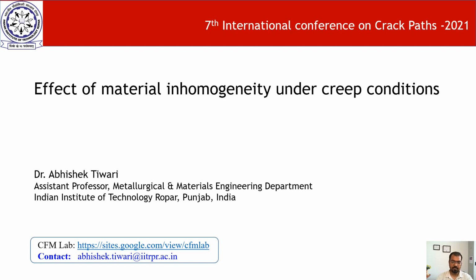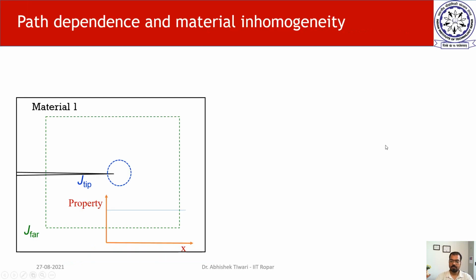So if we have a homogeneous material which is cracked, homogeneous meaning the material is same everywhere and the properties are same everywhere, and if I evaluate the value of J integral at a contour which is very close to the crack tip and at a contour which is far away from the crack tip, I will get the same value because this J integral defines the singularity, and there is only one singularity.